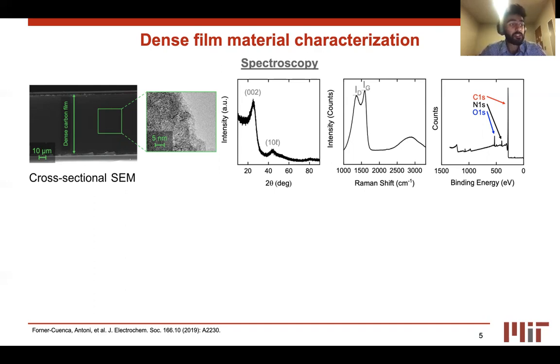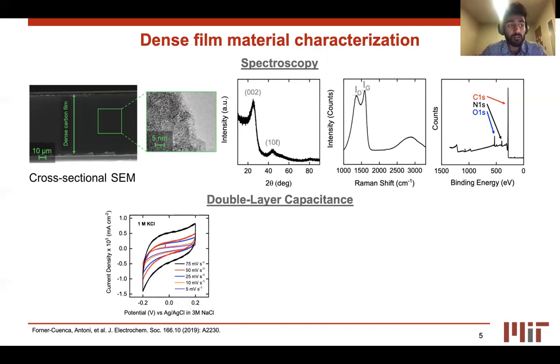In addition, the XPS spectra on the right indicates the presence of carbon, nitrogen, and oxygen functional groups as expected for the bottom-up synthetic procedure described for producing the carbonaceous, non-porous, and planar carbon films. The electrochemically active surface area was also estimated.